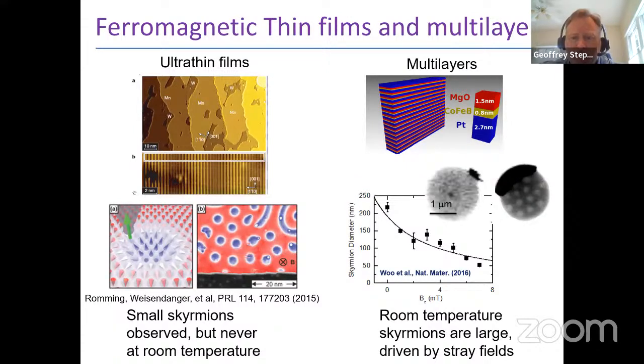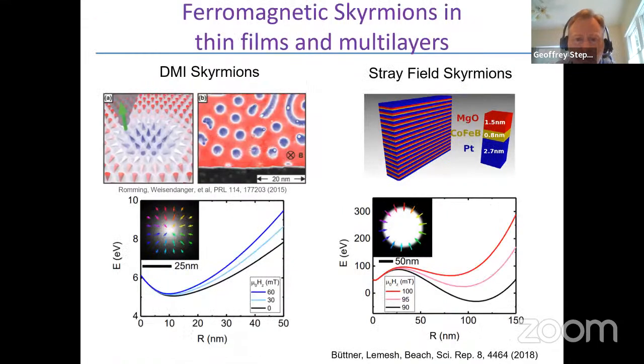And in that case, those kinds of sizes are only achieved by applying external magnetic fields that can squeeze the magnetic skyrmions down. And the reason for that is that in a single film, in a very thin film versus a multilayer stack, the stray fields are very different. And as we've shown in the publication shown down at the bottom right, it is these stray field interactions that make it relatively easy to create and stabilize magnetic skyrmions in multilayer stacks. While these stacks have DMI, in a single layer film, the kinds of films that have been explored by spin polarized STM, it is the DMI that is primarily responsible for the stability of a skyrmion.